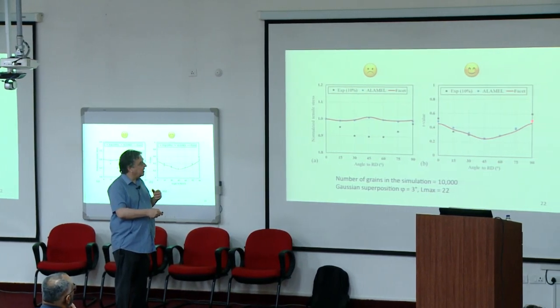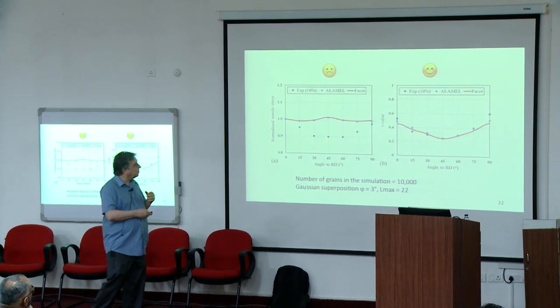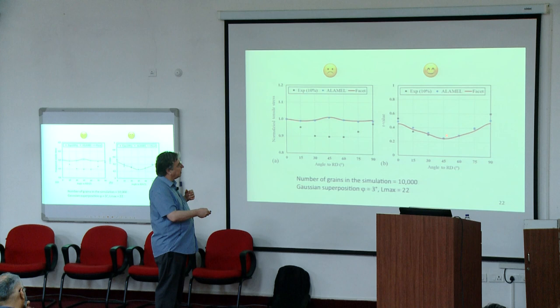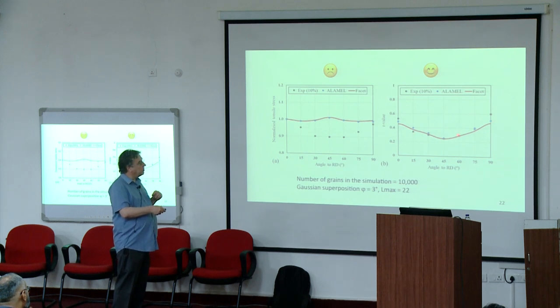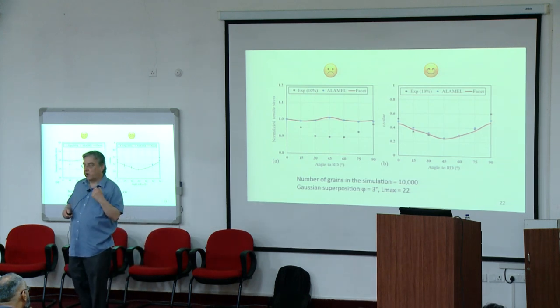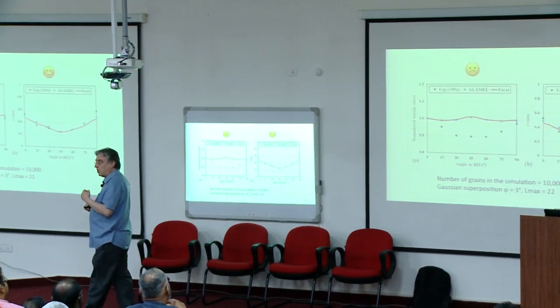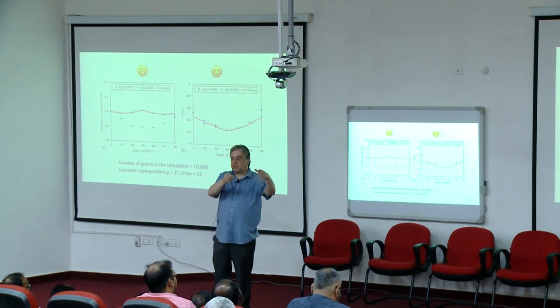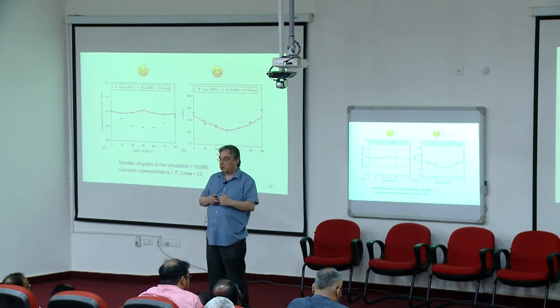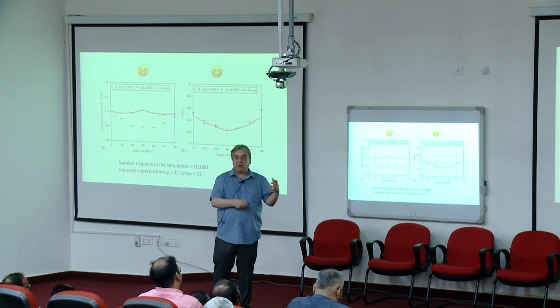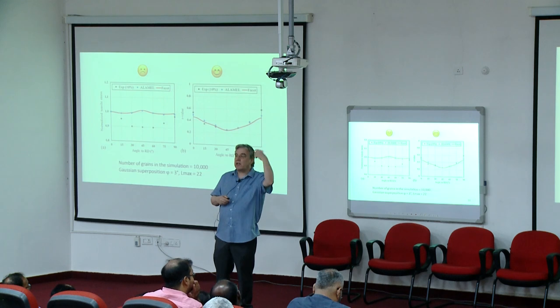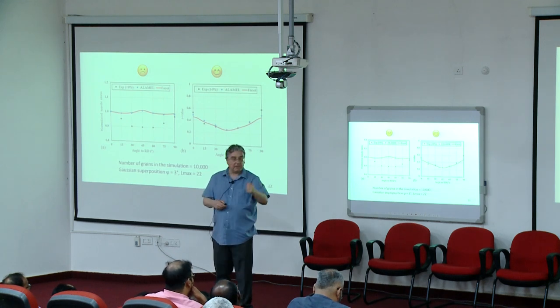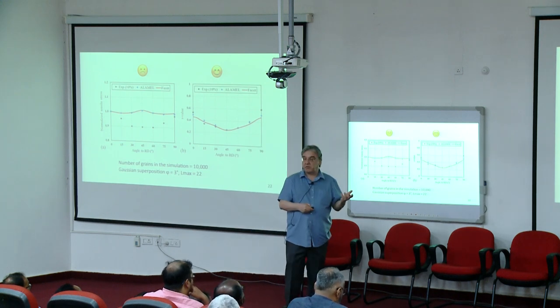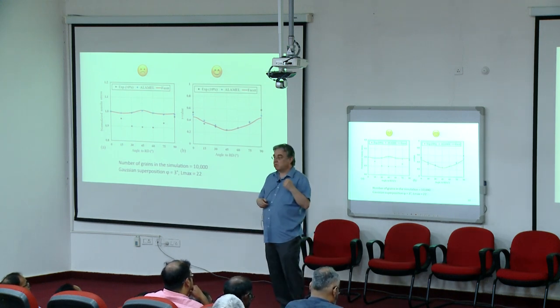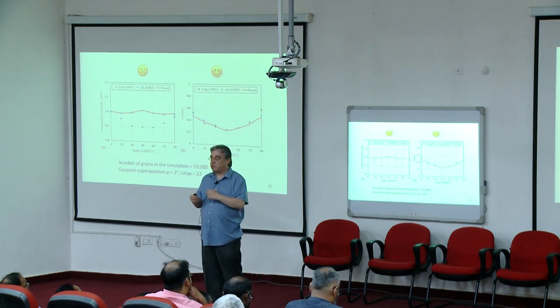Now, you can see that if you model the R value, these are experimental data, and these are model data. We have two different models, but I'm not going into depth. The correspondence with the R value, and hence the earing behavior, is quite good in detail. This means that if you know this set of n crystallographic grains, this distribution function of crystallographic orientation as a microstructural state variable, this is the analog of the grain size in the Hall-Petch relation, then from that point on, if you have a good crystal plasticity model, we can predict the earing behavior. So that's a powerful structure-property relation.